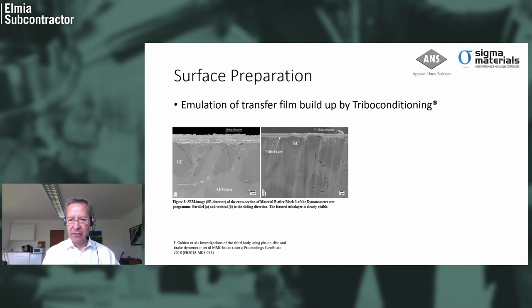This is an example from Audi, shown here with hard particles, silicon carbide, in a matrix. And you can see that there is this film formation in the thickness of 0.2 to 1 micrometer. And it is mainly between the hard particles on the soft matrix. It has an amorphous structure or contains very tiny abrasive particles. And also in the left picture, you can see a little bit of a shattered silicon carbide particle if you look close enough. So carry on, please.